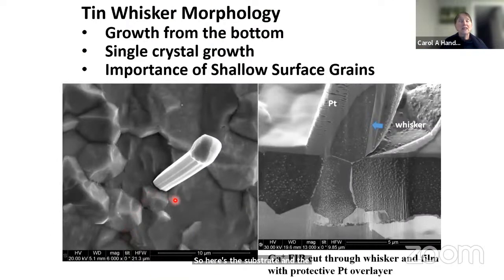Well, the way it takes place is that there are some particular grains in the structure, we'll get to exactly why and how, that can become a longer range sink for atoms. So diffusion happens over, not just in a single grain, but over multiple grains. And there's growth of the whiskers. So there's the substrate, and the oxide suppresses diffusional creep. So this is a typical microstructure. This is a whisker coming out at you.